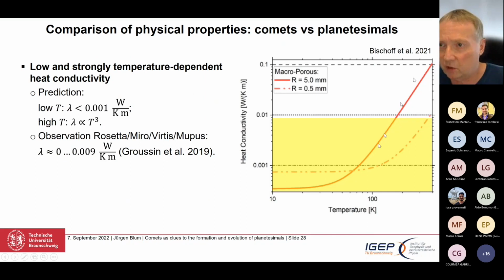As mentioned before, you've seen that chart from Bischoff et al. 2021: the heat conductivity as a function of temperature. This prediction faces the observations summarized by Groussin et al. 2019, that the heat conductivity from different instruments combined, there might be deviations at individual instrument level up or down, might be as small or smaller than roughly 10 to the -2. So this is the yellow marked region, and you're seeing for 5 millimeter pebbles, this basically fills the temperatures that were present. So again, it's not a proof, but it's completely in agreement with the pebble pile model.